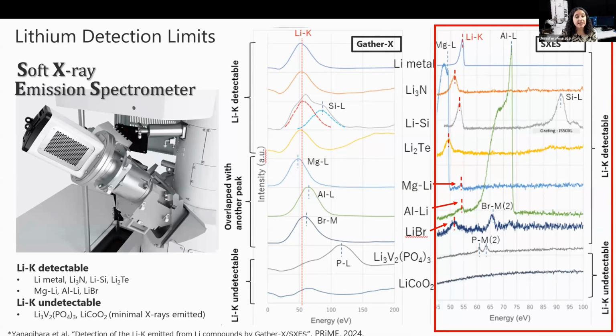But for these samples, in each of those alloys where the peaks were too overlapped, with the SXES detector, the lithium can now easily be detected, and the peaks are even completely separated, even in the case of magnesium, where the peak separation is only around 5 eV. So note that even using this new SXES grating, which is specialized for lithium compounds, this experiment did not detect lithium in the two bottom battery materials that involve lithium and oxygen.